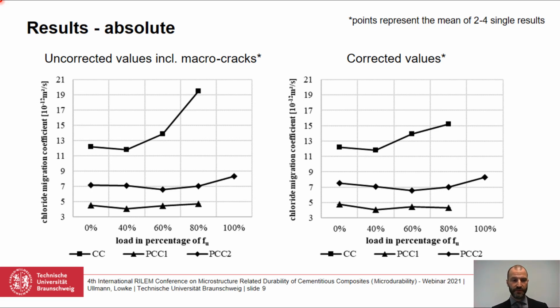What we see is that the non-steady state chloride migration coefficient of the cement mortar changes significantly due to the applied load, and it changes significantly from the point of up to 50% on. And that is also for the corrected values, as we see. Not as heavy, but it can also be detected. But what we also see is that the PCC mortars are almost not affected by the external load. Only if we apply up to 100%, almost 100%, then we can see a slight increase. But if you want, we can also try to interpret a decrease of the chloride migration coefficient, a slight one.